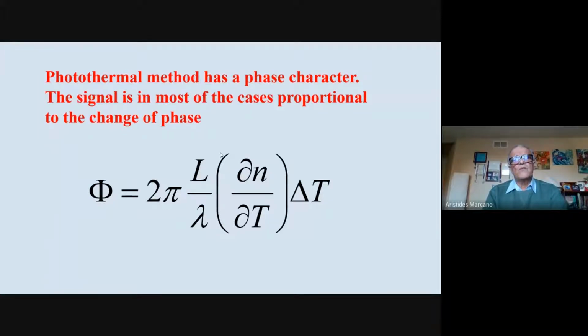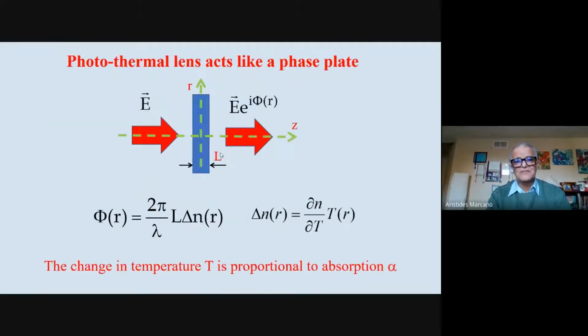But actually, we worked with some people doing this interferometry back in Venezuela, Professor Escalona. And he actually didn't believe that the photothermal method is so sensitive. And I told him that the sensitivity is similar to interferometry because it's a phase method. He didn't believe that, and he tried to demonstrate that photothermal lensing is less sensitive, but he discovered that it's not. They exhibit more or less the same sensitivity, and we made an excellent paper about that together with him. He was very suspicious about this photothermal lensing, but we just demonstrated that it's similar to interferometry in this case.